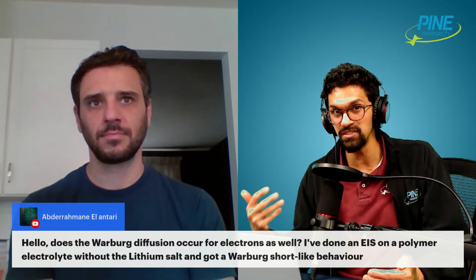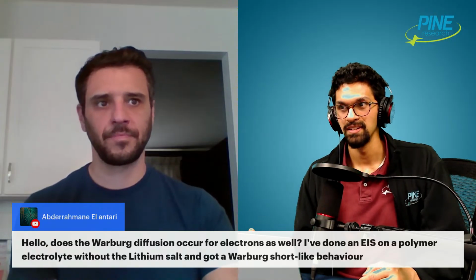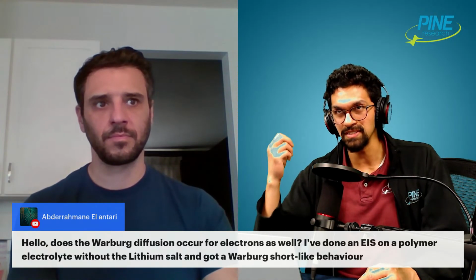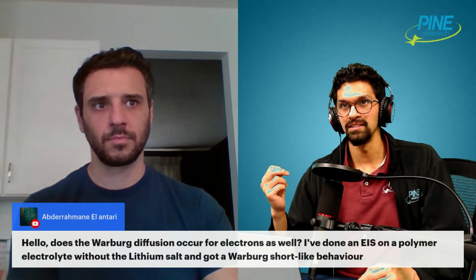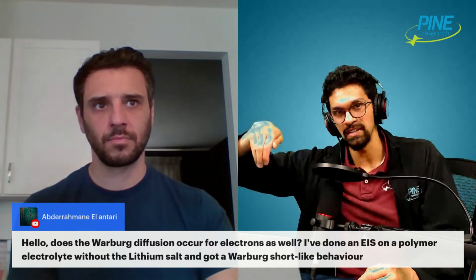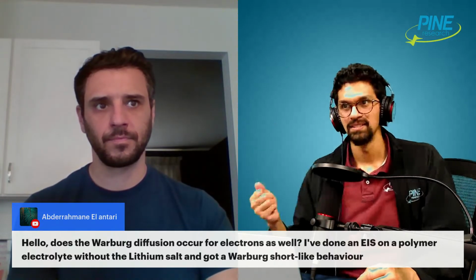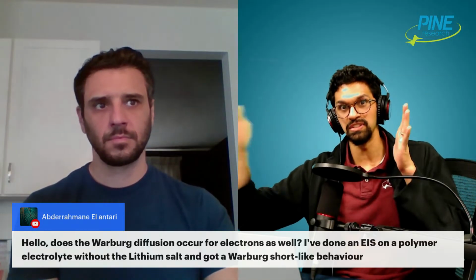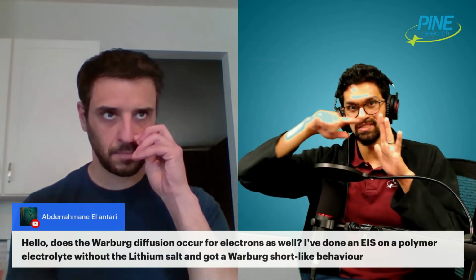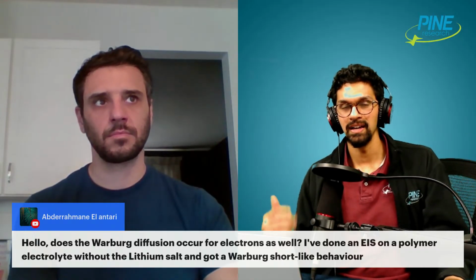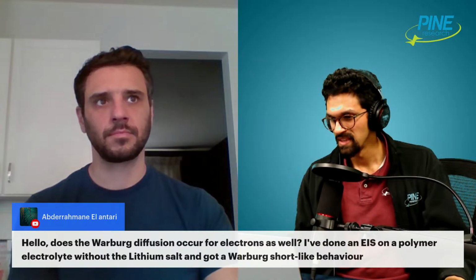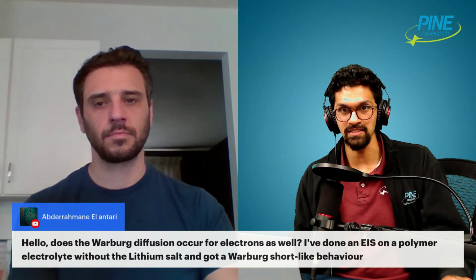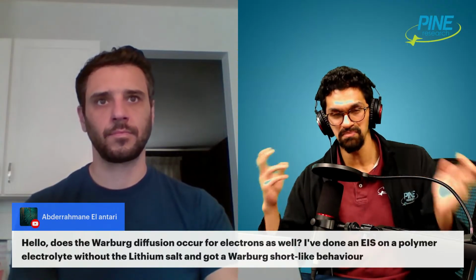Now, even though you didn't pre-soak it with the electrolyte, on the time scale of the short, which is where you're getting that curl that hits the x-axis, that's enough time for an ion from solution to go all the way from one end of the electrode to the other end to grab charge. And so on that time scale, it has plenty of time to pass charge between those two sides through an electrolyte that doesn't have the lithium salt or the lithium ion, so it then acts as, I don't want to say a short circuit, but you only have the quote real impedance at that stage. So that's what I think about when you describe this.